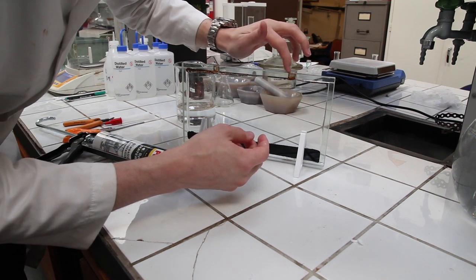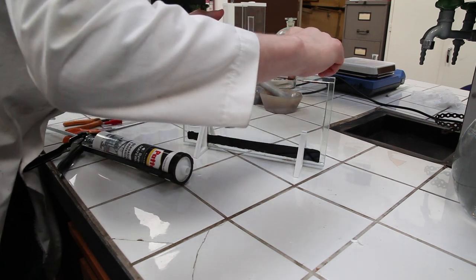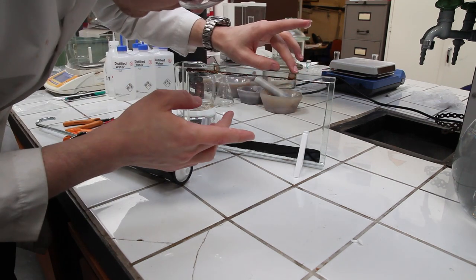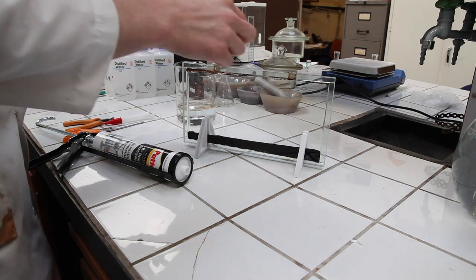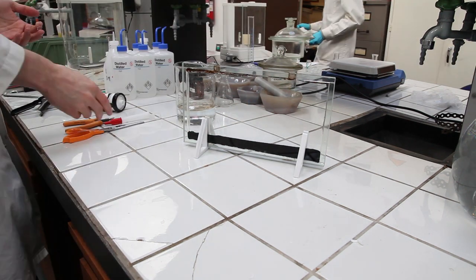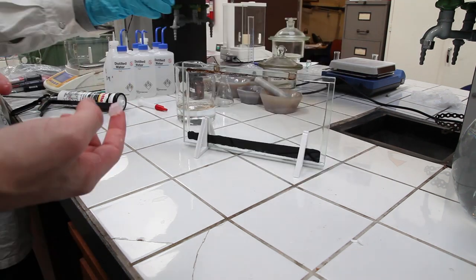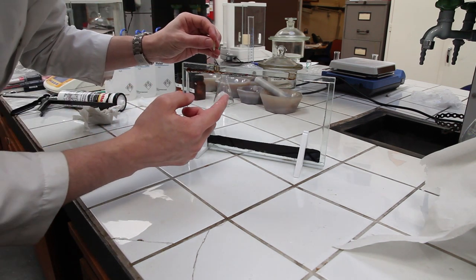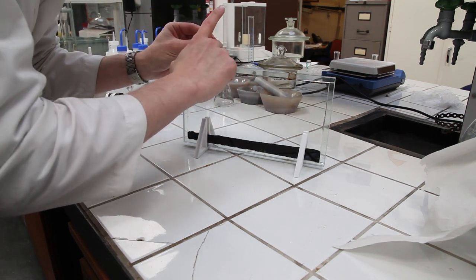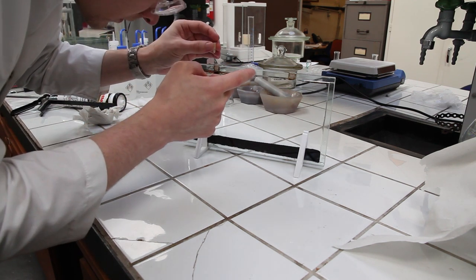Casey Hughes, the guy with the awesome kinetic ferrofluid sculptures that we gave a shout out to in the previous episode, has informed us that if you want the display to last a long time, any kind of sealant that has to be used should never come in contact with the ferrofluid. This includes silicone and the epoxy that binds the glass plates together. We'll probably keep using silicone in our future displays because it's so much more convenient and cheaper than the alternatives. But if you want a seriously long-lived display, these are the measures you will have to take.